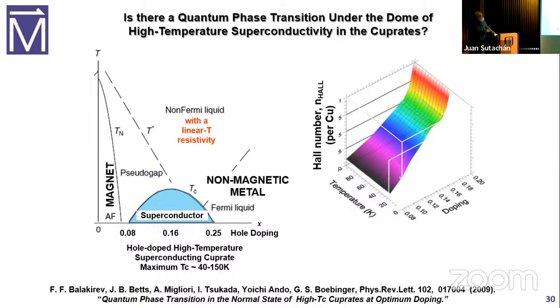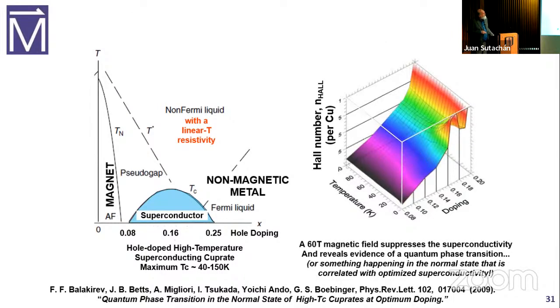But if you look up at 100 Kelvin, so now you're way up above here, and you go across, the number of carriers in your material goes up as you increase the doping, which is donating carriers. Nothing mysterious there, but in order to know what's happening at 0 temperature, we have to apply 60 Tesla magnetic fields, and then we see something really bizarre.